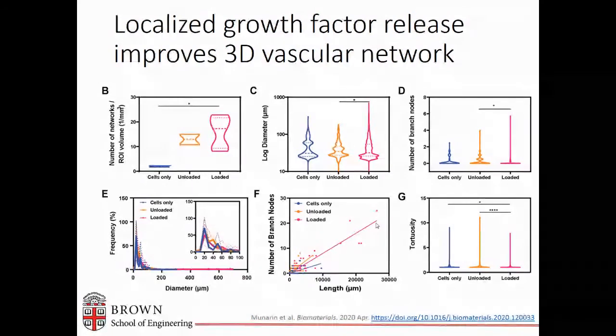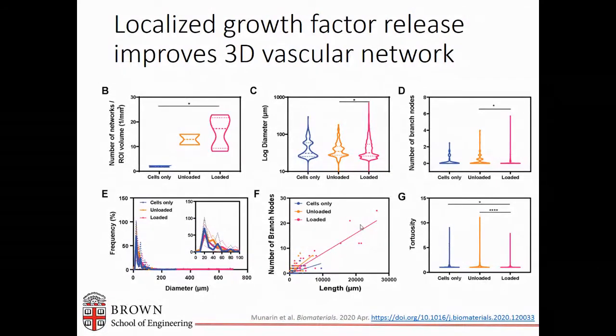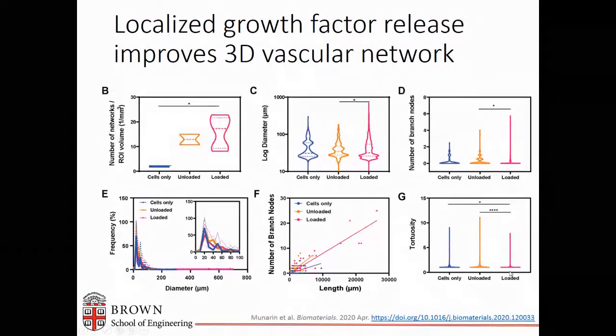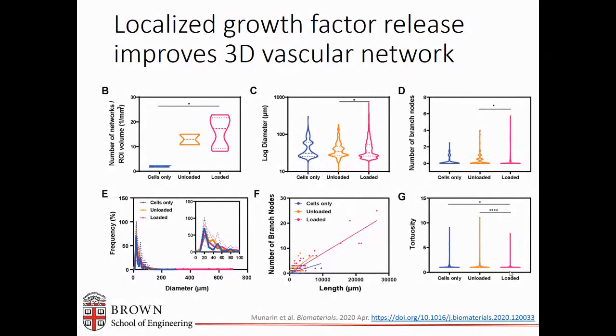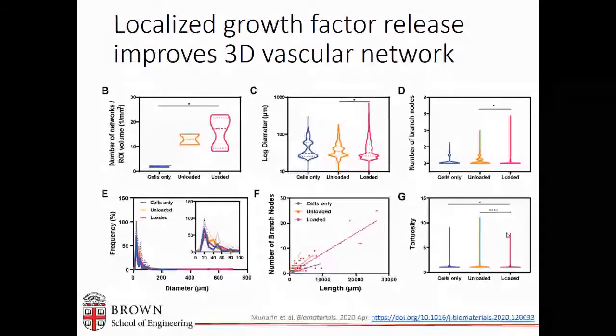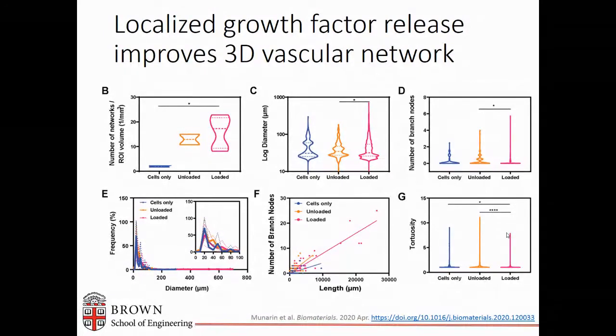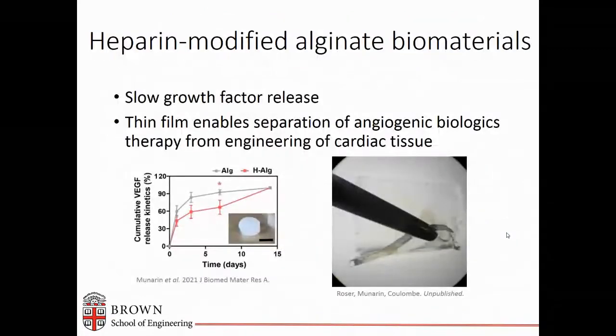It was really interesting to us to also find that the tortuosity of these three-dimensional reconstructed vessels in the implants was decreased. We know that tortuosity is inversely proportional to flow, and so we believe that decreased tortuosity could lead to a better perfused vascular bed with greater flow velocities. That is to be determined as this was all done at sacrifice and is a static assessment.